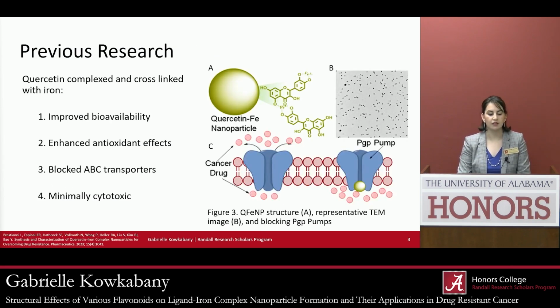So previously in my lab, we have worked with quercetin, which is one of these flavonoids, in order to try to overcome these limitations. In order to do this, we have taken quercetin and used iron to form a metal complex, and then used excess iron to form a nanoparticle. And in preliminary cellular findings, we showed that this improved bioavailability of quercetin, enhanced its anticancer and antioxidant effects, blocked ABC transporters, which is a key mechanism of drug resistance, and these nanoparticles were found to be minimally cytotoxic.